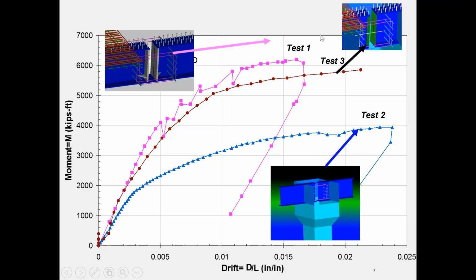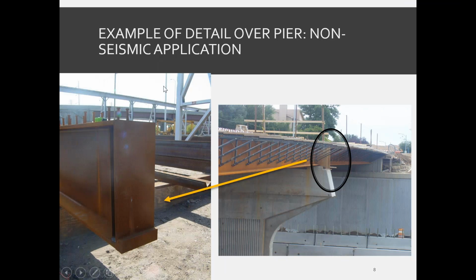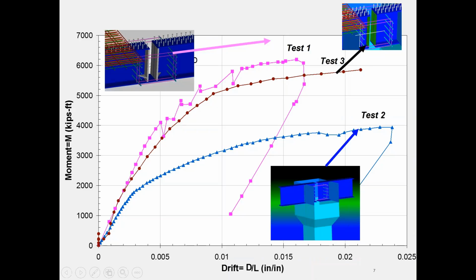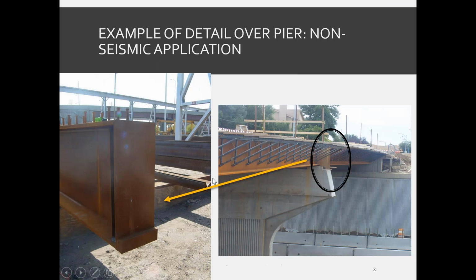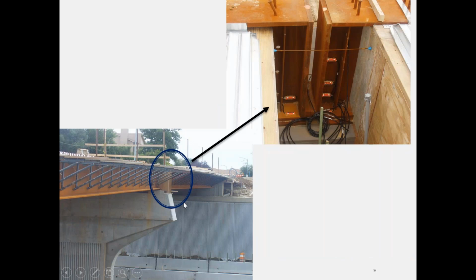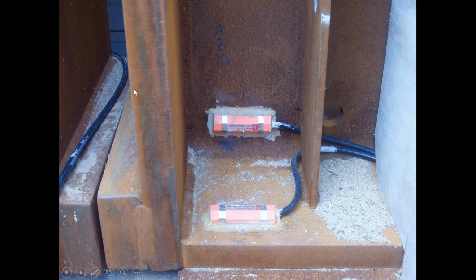Now, as far as this gap goes, there have been many of these bridges in service. There have been many of these bridges that have been constructed. And our recommendation is that as long as you have maybe about 1 inch or so gap, you don't have to have a full contact. It's a good idea to have a contact here, okay? Like you see here, it's good to have a contact, but even if there was a gap, I wouldn't worry about it because the paste is going to go and fill it up, and it's going to be predominantly compression.